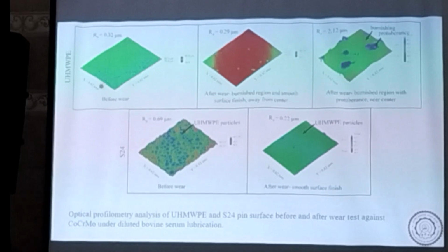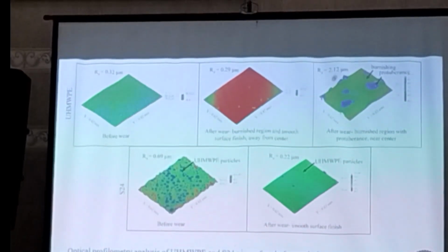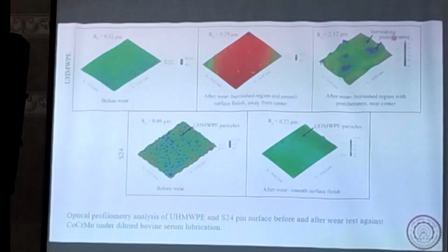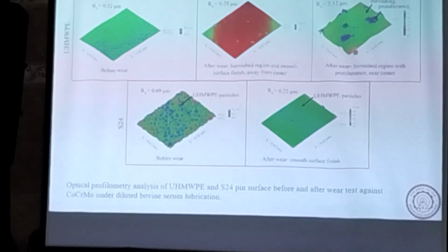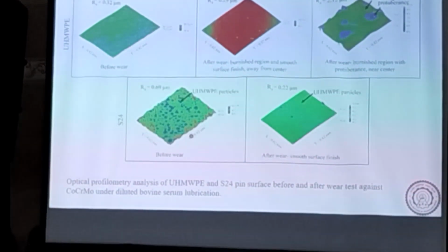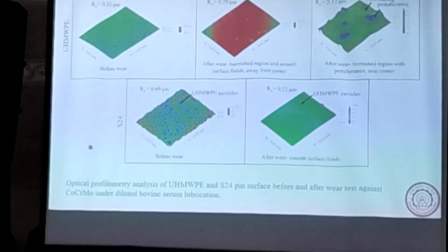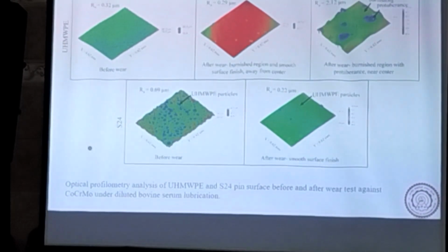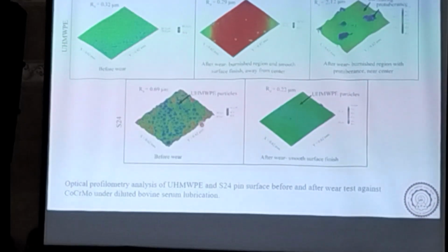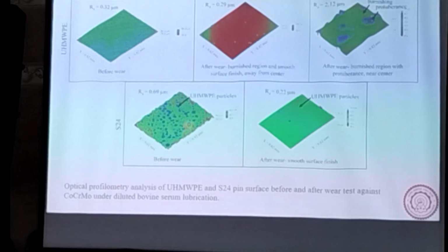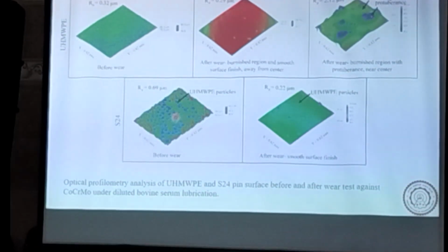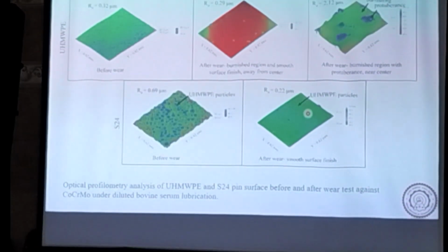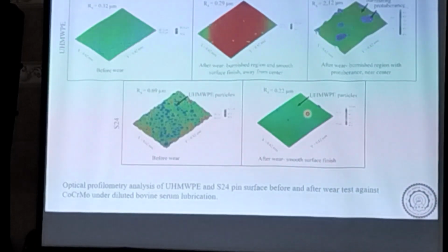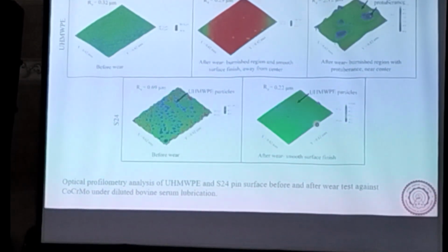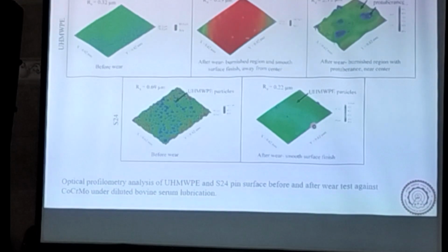So in the case of pure UHMWPE, we can see a lot of plastic deformation, a lot of bulk deformation, which increases the friction. Whereas in the case of this 24% UHMWPE with Structalit, we see that these UHMWPE particles cover the surface, and we end up with a very, very smooth surface, a low shearing smooth surface, and that gives us low friction.